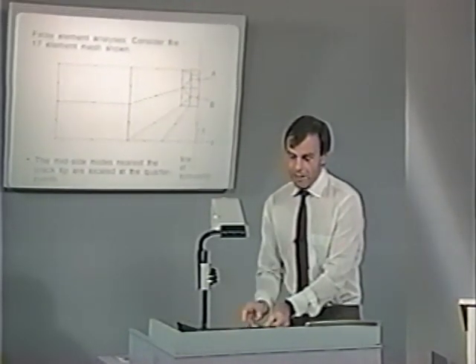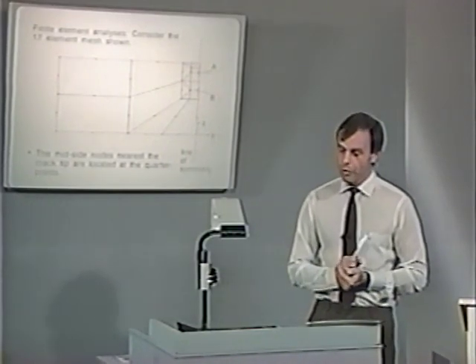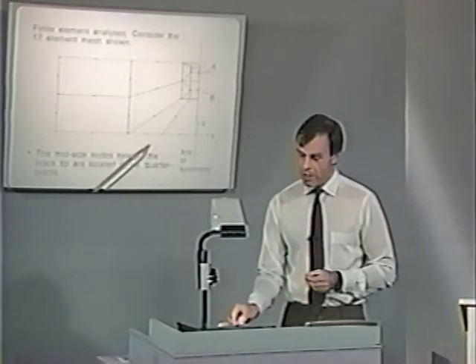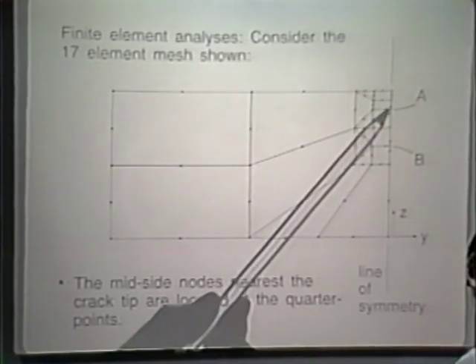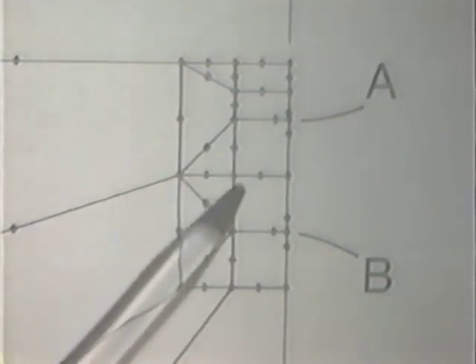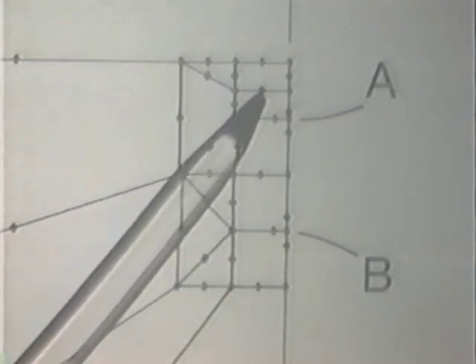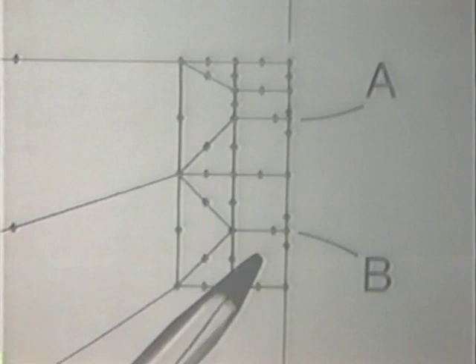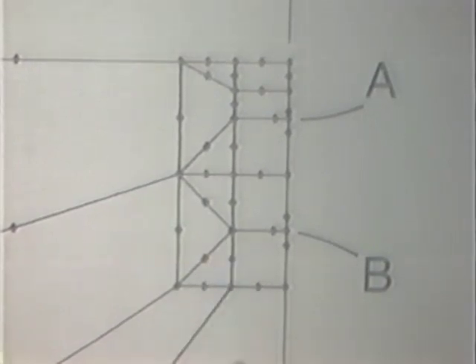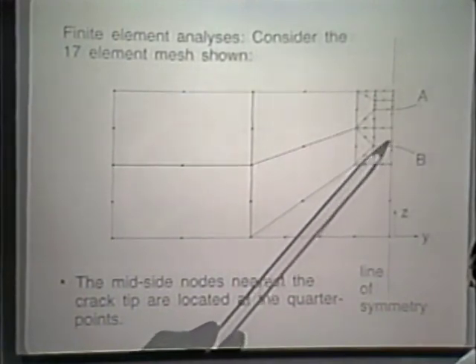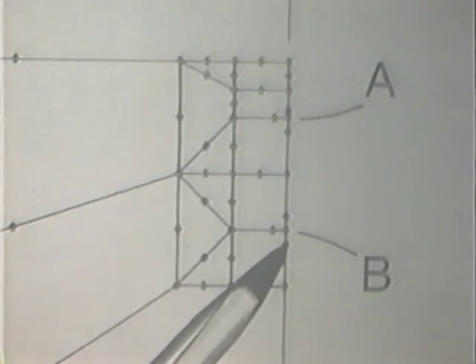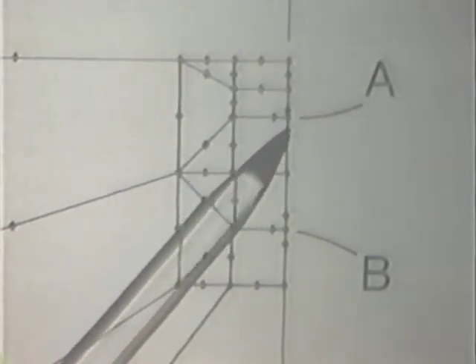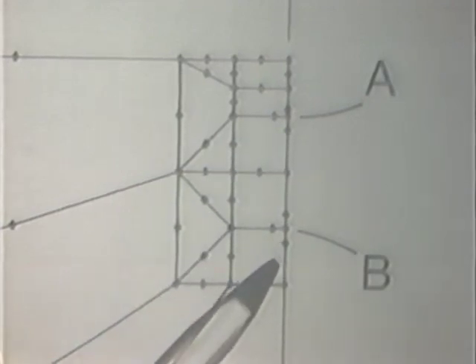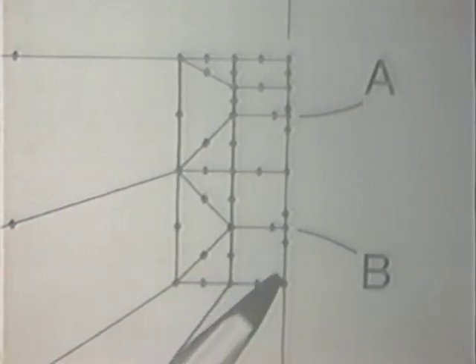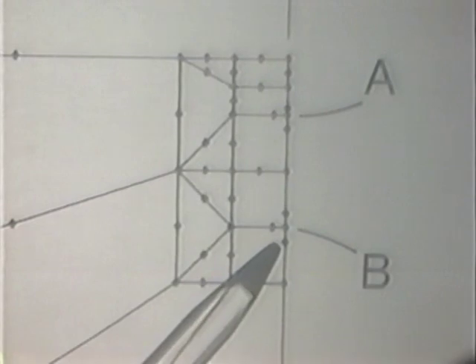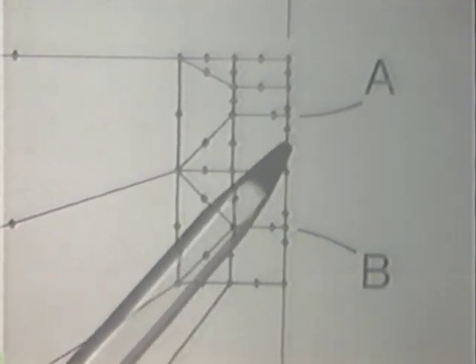Let's look at the results. Finite element analyses have been performed using a 17-element mesh, and this is the mesh here. We call this the coarse mesh. Notice the crack is right there. Notice that we have only two elements above the crack to the boundary of the plate, and once again, only two elements below it. Notice that these nodes around the crack tip B have been moved to the quarter point. And similarly, they have been moved here to the quarter point, meaning that this node is not at the midpoint of this element side, but at the quarter point of that element side, and similarly for the other nodes around the crack tips.